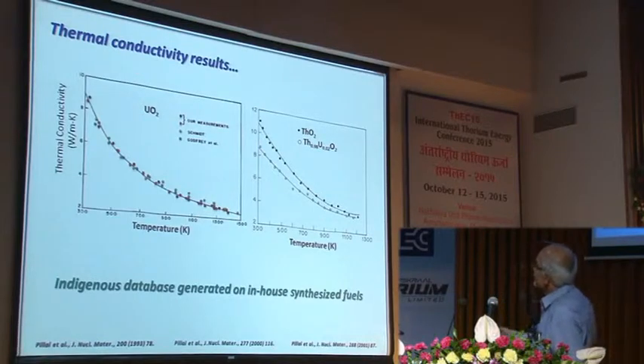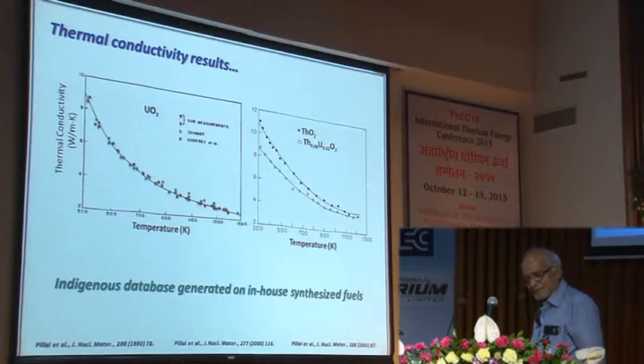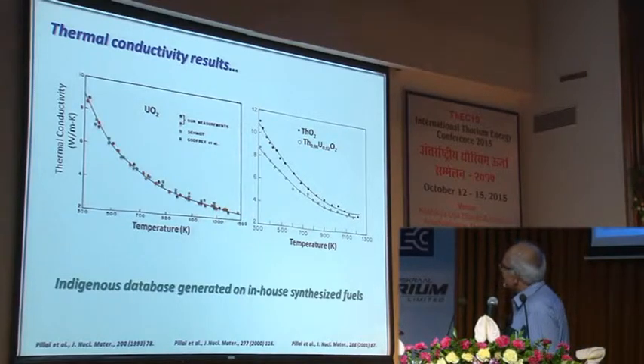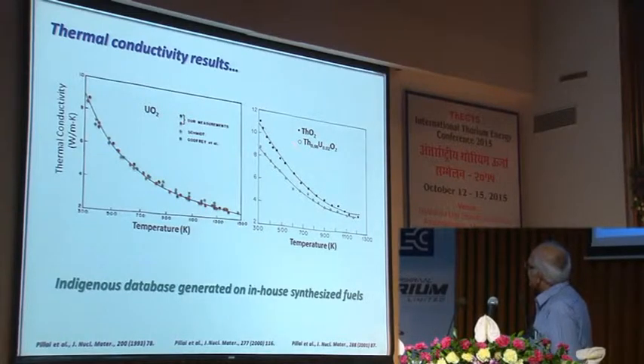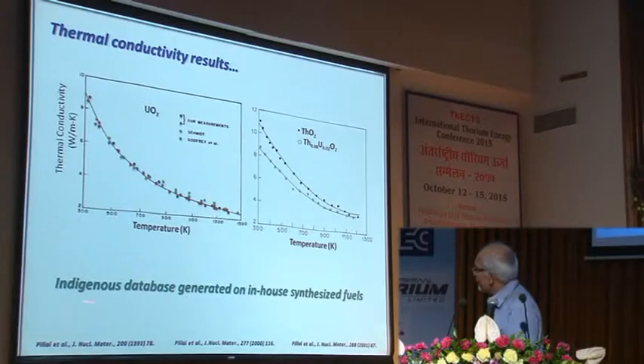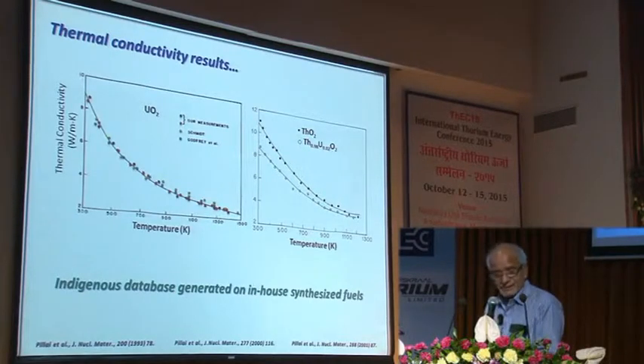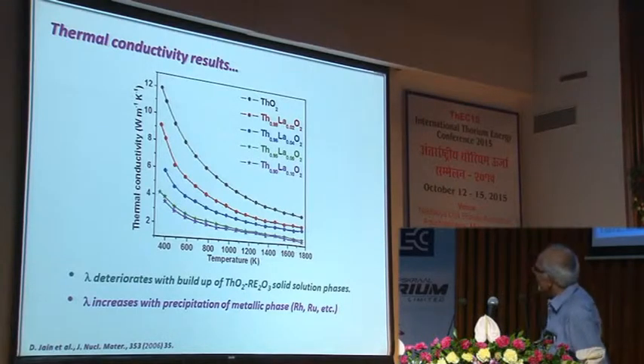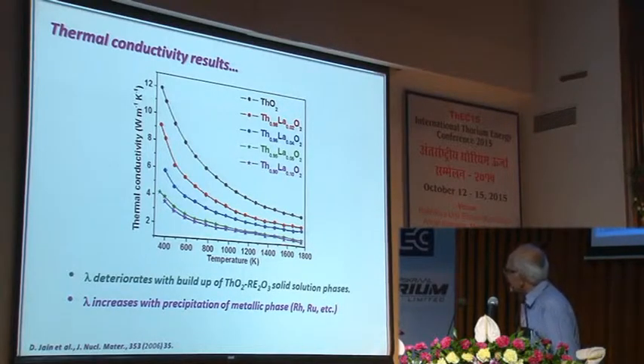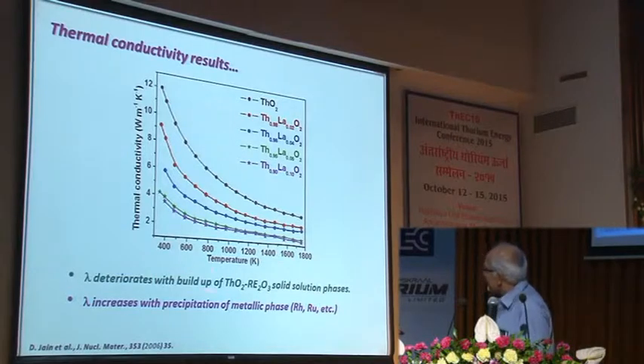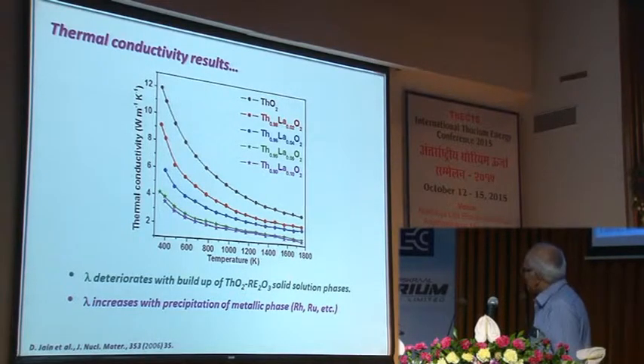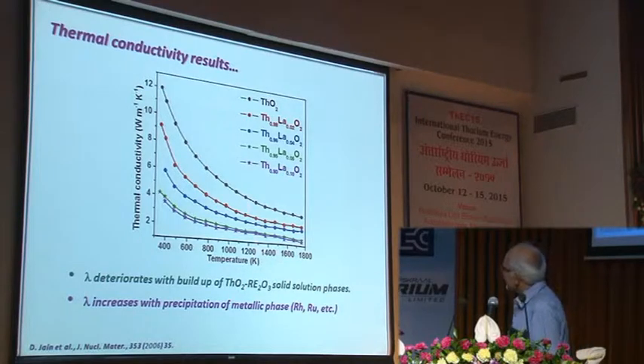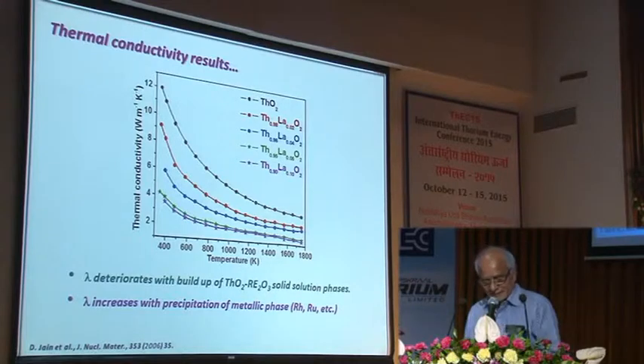For example, here are the thermal conductivity results. Since we are using indigenously developed equipment and getting high quality data, this is the representation. This is the thermal conductivity of UO2, and you can see how our results match beautifully with the other results. And this is the result for thoria and the thorium uranium oxide. And we have built the indigenous database with the in-house synthesized fuels. This one was shown by Dr. Ramkumar. As the lanthanum content increases in the thoria fuel, the thermal conductivity decreases. So the lambda deteriorates with the buildup of thoria rare earth oxide solid solution phases, and one which has not been shown here, it also increases with the precipitation of metallic phases.